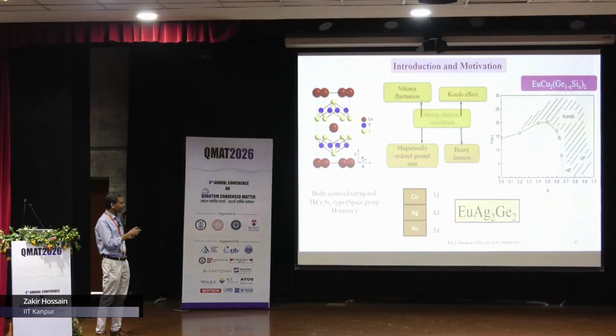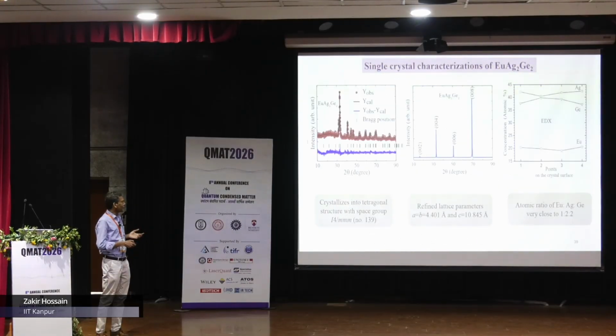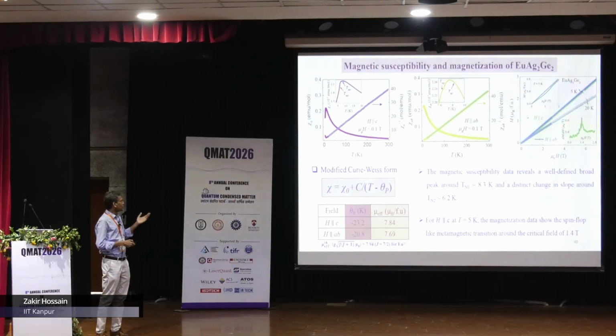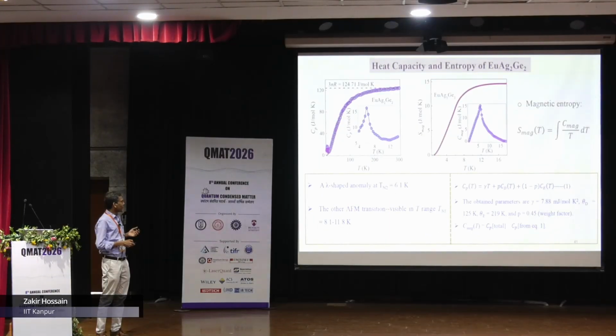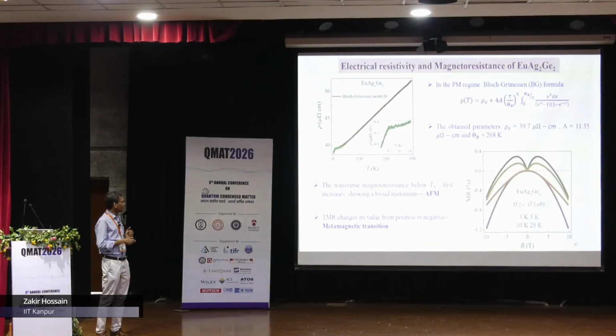This was the first work we did, and we did europium copper two germanium two silicon doping long ago. In that context, and also in the context of topological materials, we synthesized this compound. I will just go to the main result. It's also antiferromagnetic, and heat capacity also confirms the bulk nature of the antiferromagnetism.